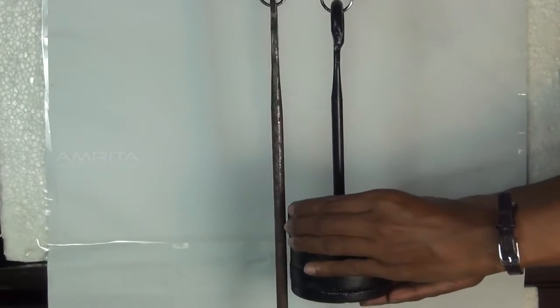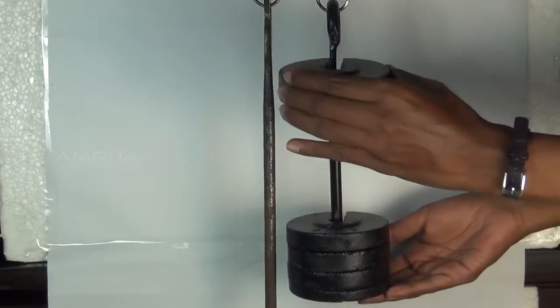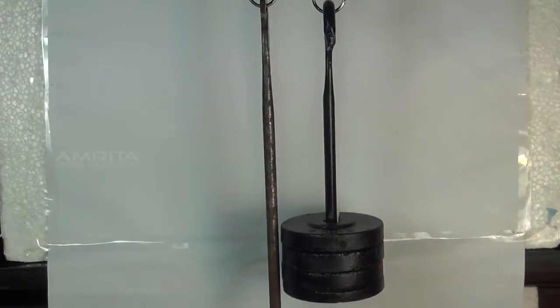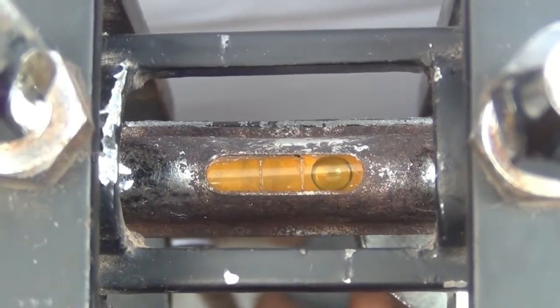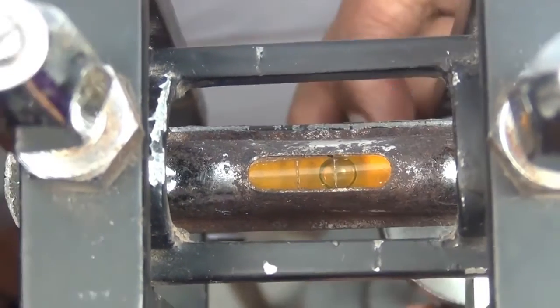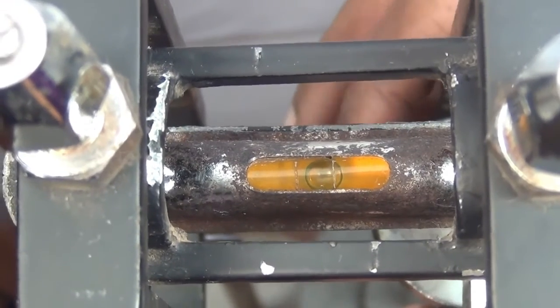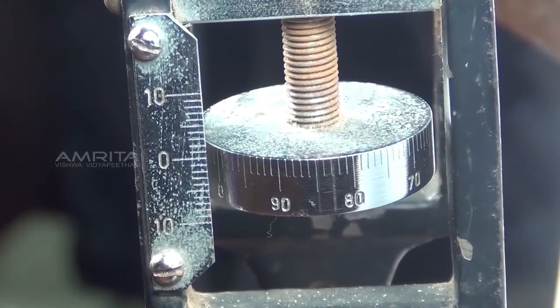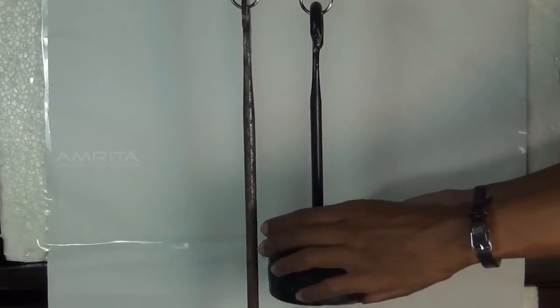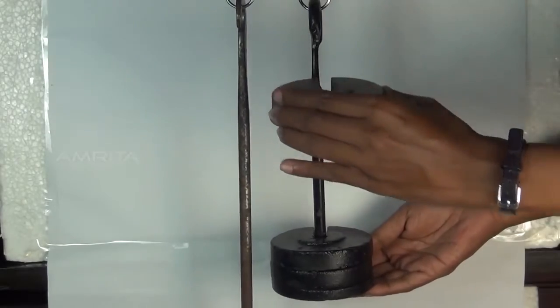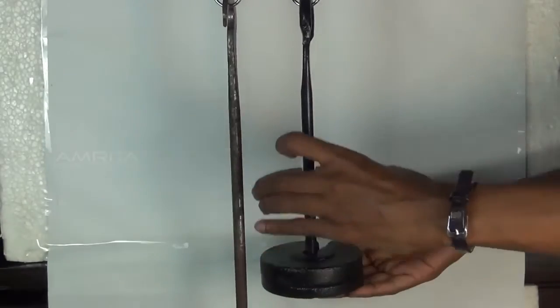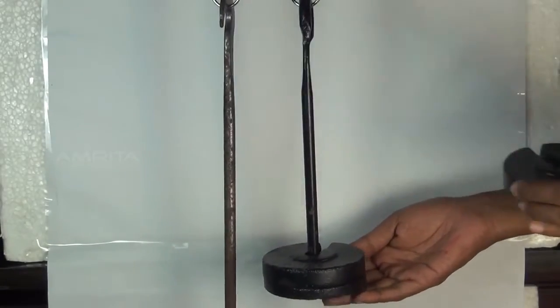Now, remove one 0.5 kilogram weight from the weight hanger. It can be noted that the bubble shifts to the right side. Bring the bubble to the middle by adjusting the central screw and note the readings. Repeat the above process by removing weights in equal steps of 0.5 kilograms.